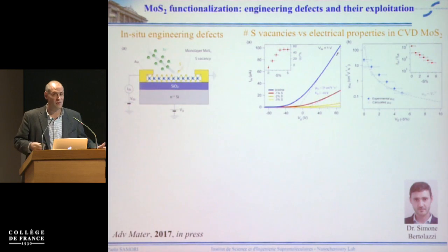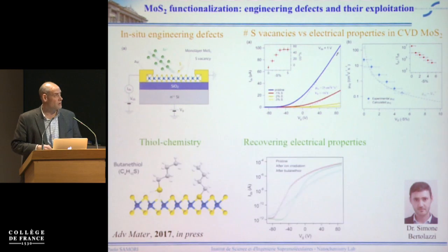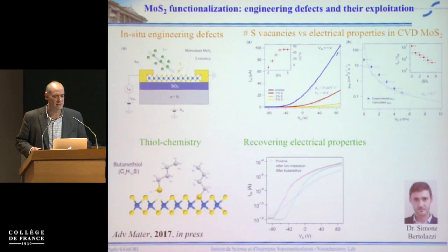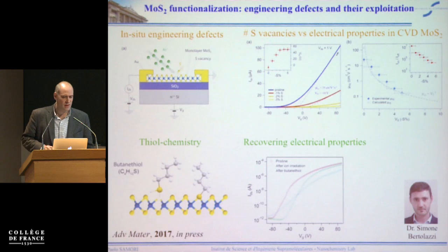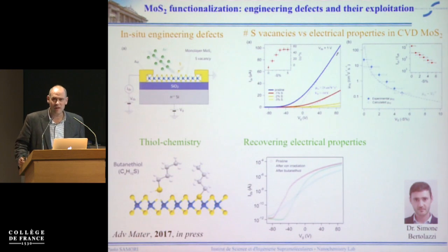And then the question is, you create all these defects, and can you make use of them? Of course, yes. So the idea that we played with here was a very simple molecule like butanethiol, and we use this in order to fill these defects. So we start from the IV characteristics in our back-gated field effect transistor, where you have the pristine device here. After 2% of sulfur vacancy, you can see that the IV characteristics are much more modest. You can gain it back by functionalization with thiol chemistry, so with butanethiol.